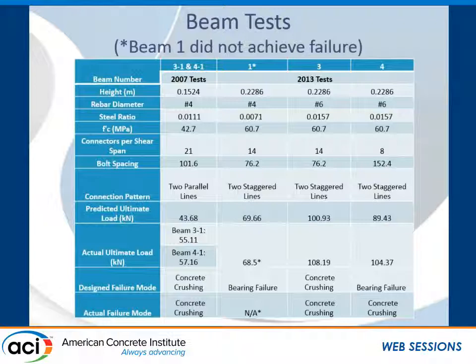Concrete compressive strengths were 40 and 60 megapascals, while the steel ratios for the beams ranged from 0.71 to 1.57%, so very ductile beams. There was significant variation in the number of fasteners in each shear span, with bolt spacings ranging from 75 to 150 millimeters, with bolts in either 2 parallel rows or with a staggered pattern of 1 bolt per row. This slide also shows a comparison of the ultimate loads and failure modes.